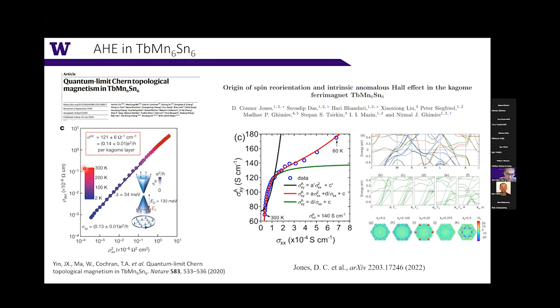They found that there's a large intrinsic anomalous Hall effect in this system, which they obtained by doing this power law scaling fitting of rho anomalous Hall versus rho xx squared. By extracting the constant and the quadratic coefficient, you can separate the intrinsic and skew scattering parts, and obtain an intrinsic anomalous Hall conductivity of about 121 Siemens per centimeter, corresponding to 0.14 e squared over h.